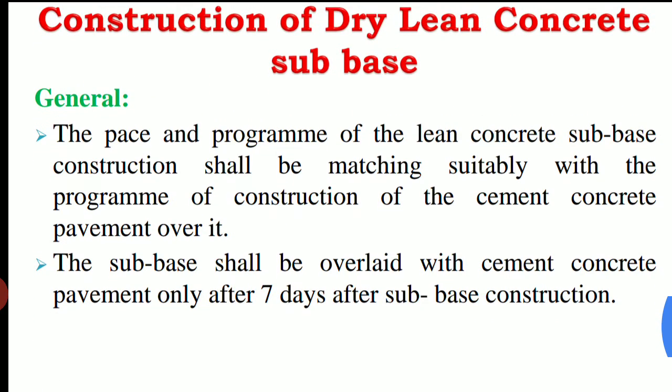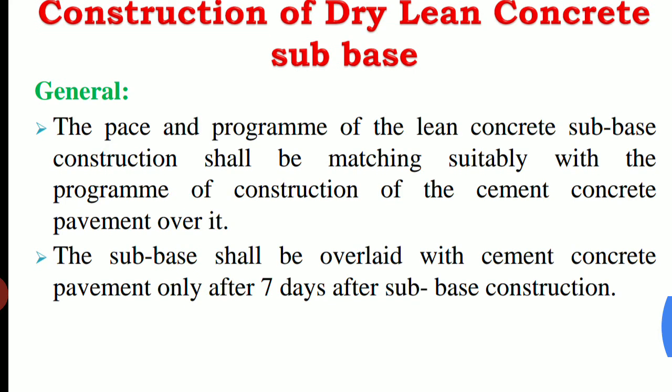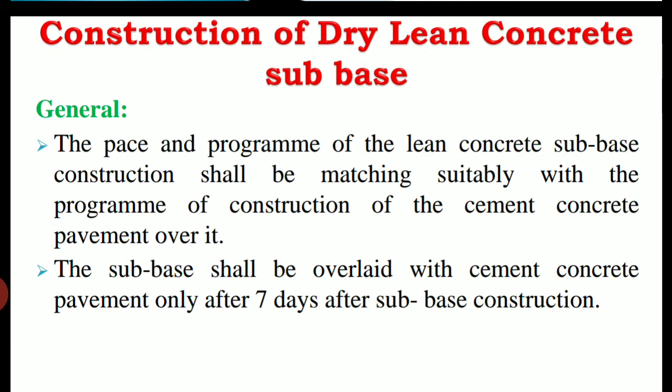And then the construction of dry lean concrete sub base. So here the placing and performance of the lean concrete of the sub base construction shall be matching suitably with the program of construction of the cement concrete pavement over it. The subbase shall be overlaid with a cement concrete pavement only after 7 days of the subbase construction. So here they have given the conditions: whatever subbase layer there is will be overlaid with the cement concrete pavement only after 7 days after the subbase construction.